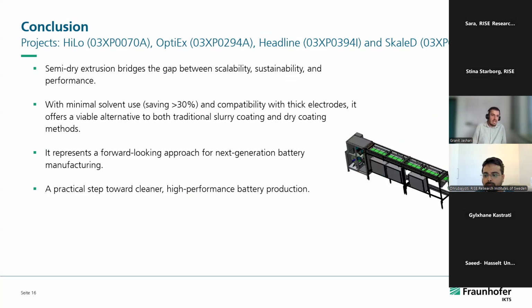As the conclusion, I would say the semi-dry extrusion process bridges the gap between scalability, sustainability, and performance, with really minimal solvent use, saving more than 30%, and also compatibility with thick electrodes. It offers a lot of advantages as an alternative to traditional slurry coating and also dry coating, somehow making a bridge between them. It's also an approach for next generation battery manufacturing, and a good step toward a cleaner and more sustainable process chain in the whole battery manufacturing process.